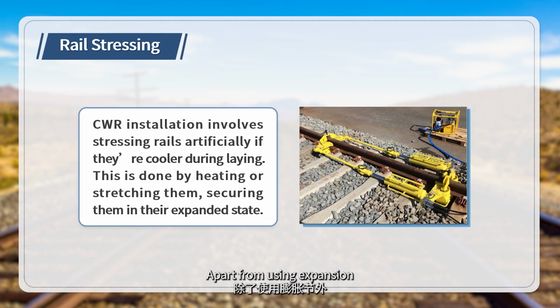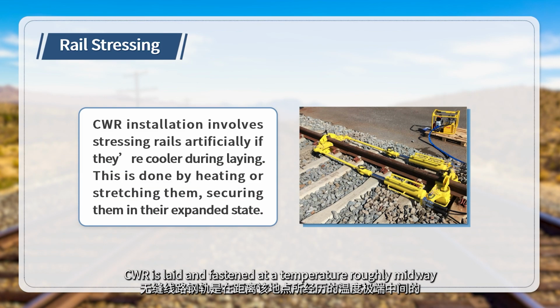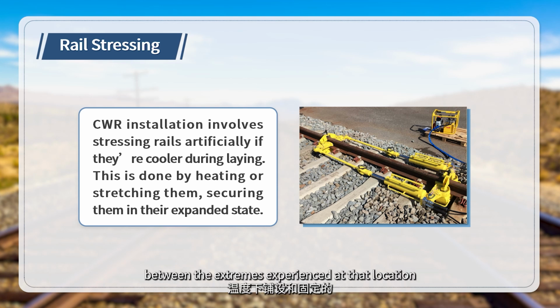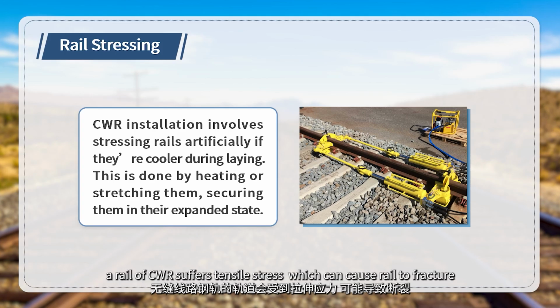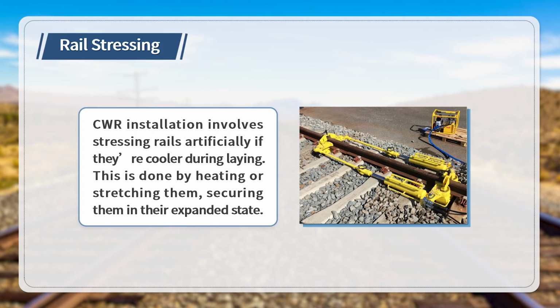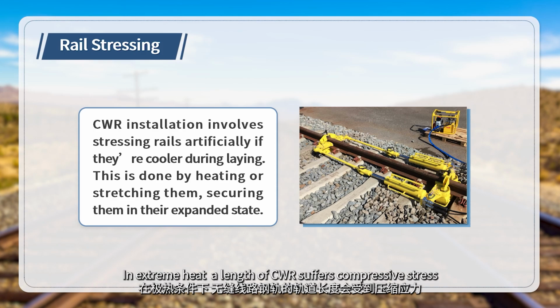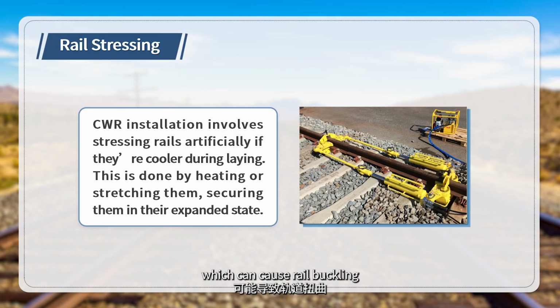Apart from using expansion joints, CWR is laid and fastened at a temperature roughly midway between the extremes experienced at that location, and this is known as the rail neutral temperature. This is because the steel rail contracts at low temperatures and expands at high temperatures. In extreme cold, a rail of CWR suffers tensile stress, which can cause the rail to fracture. In extreme heat, the length of CWR suffers compressive stress, which can cause rail buckling.